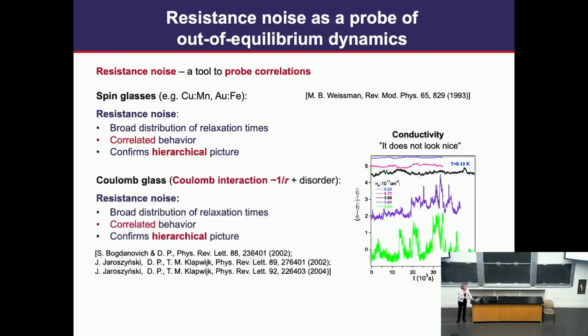And then some years later, we actually looked at the noise in this Coulomb glass case with the long-range Coulomb interaction. These are actually some of our data. You can see that the noise, relative fluctuation of conductivity, are of the order of 100%. From this, you can extract a lot of information about correlations, and we found behavior very similar to what was found in spin glasses, again consistent with this hierarchical picture.